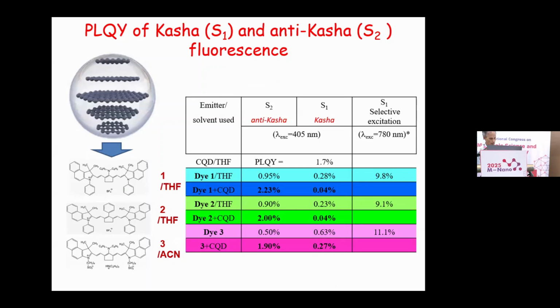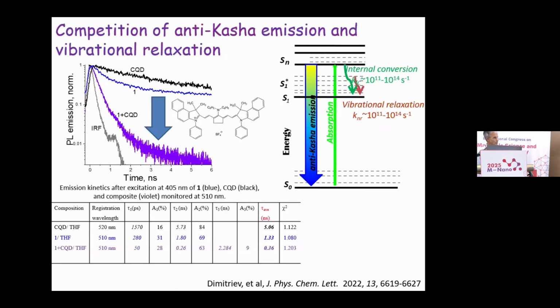Here you can see how the quantum yield of the Kasha and Anti-Kasha emission changes when we add carbon nanoparticles. For example, for this dye, addition of nanoparticles increases the quantum yield of emission by a factor of 2. For this dye, the quantum yield of Anti-Kasha emission increases by a factor of 4. At the same time, the quantum yield of the Kasha emission decreases when molecules interact with carbon nanoparticles. This is an interesting phenomenon, and I will try to explain the mechanism of why we see the enhancement of Anti-Kasha emission.